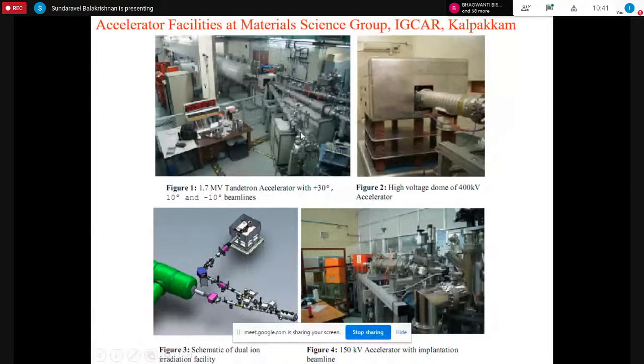In the plus 30-degree beam line, we have a high resolution RBS, where we can have an energy resolution of 1.6 keV and a depth resolution of 2 to 3 angstroms. Then there is the minus 10-degree beam line. It is a UHV beam line, and here we can do high temperature implantation under UHV conditions. This chamber is also coupled to a 400 kV accelerator with another UHV beam line. You can see this schematic, where on the sample, 2 different ions, one from the 1.7 MV Tandetron accelerator and another from the 400 kV accelerator, both meet, and we are able to do dual ion irradiation with this UHV beam line.